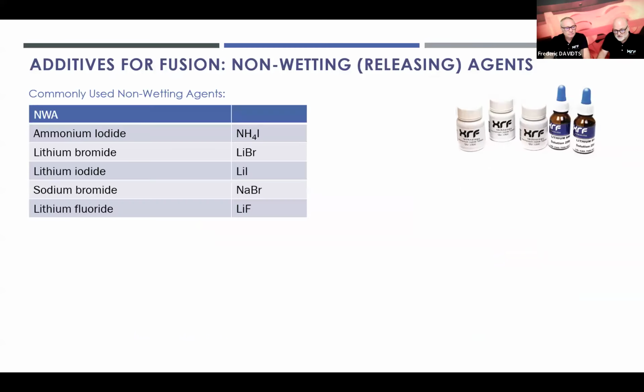The additives. So for the non-wetting agent, we have different types of non-wetting agent, and most are halogenides. The most used are lithium bromide and lithium iodide. And if you use the non-wetting agent with an automatic injection system, you will use ammonium iodide, which is available in small tablets. You can inject automatically in the crucibles during the fusion cycle. And the advantage of that is the tablets are always distributed in the crucible at the same time during the fusion cycle.